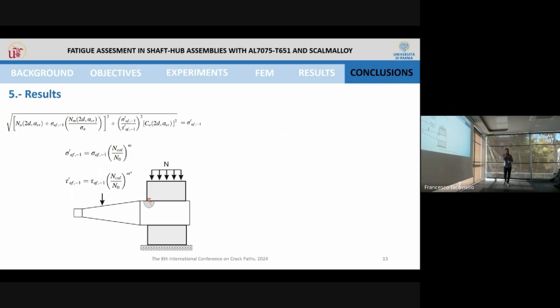Knowing the direction of the critical plane, we are going to simply apply the Carpinteri criterion. That depends, like the previous expression, on the amplitude of the normal stress to the critical plane, the mean value, also the amplitude of the tangential stress, and some fatigue parameters. It is important to remark that for this equation, we evaluate these stresses at a distance of 2D from the hotspot, not an average value. It's like a points method or something like that.